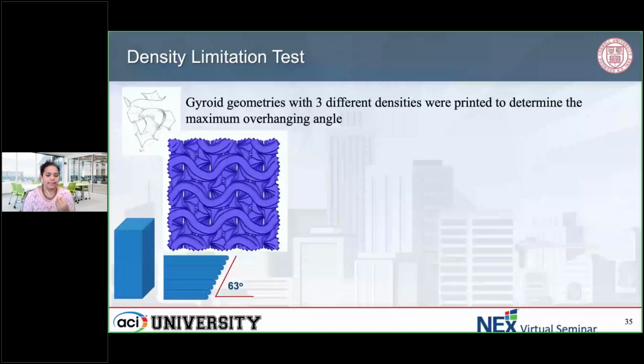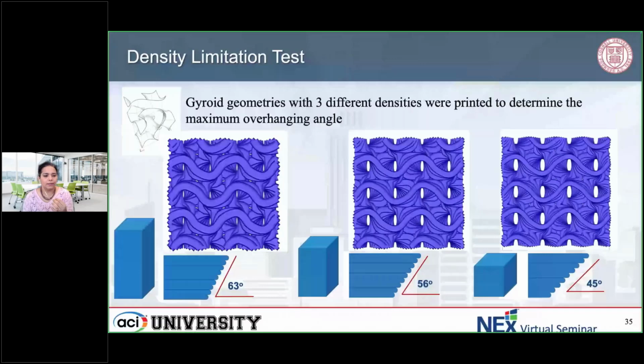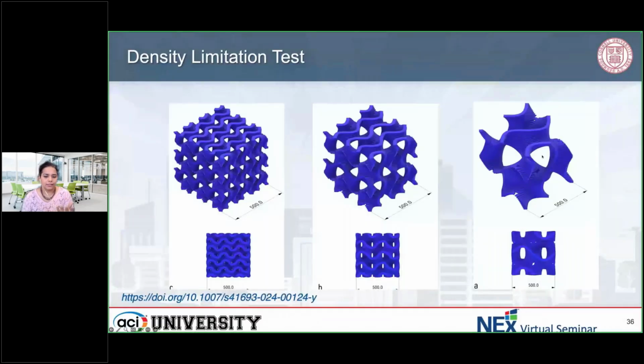So for example, in this case, you can see how the hollow space over here is really large for the case of a 45-degree angle, but in this case, you have more volume because you need a larger sine curve to fill that space. So gyroids are basically sine curves in 3 different directions, and you can stretch them in different ways to achieve the shape that you need.